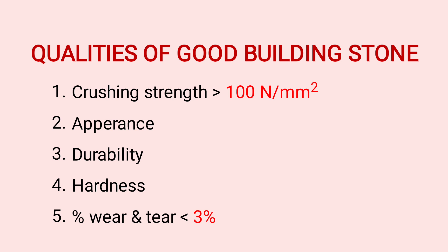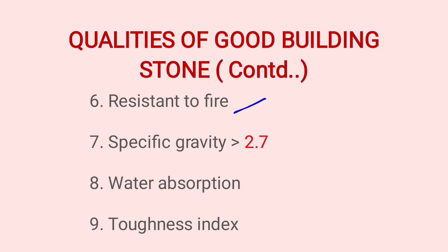Percentage wear and tear should be less than 3%. Resistance to fire is required. Specific gravity should be greater than 2.7. Water absorption should not be more than 5%. Toughness index: greater than 19 is high toughness; 13 to 19 is moderate toughness; less than 13 is not used.